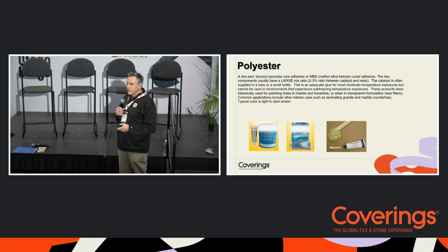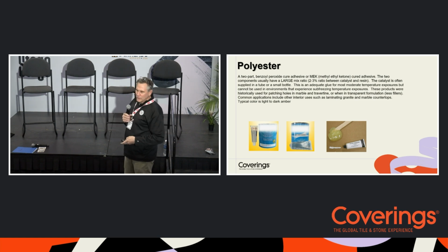And here, polyesters have probably been around for ages, and this is probably the most popular over the years. I don't recommend polyesters for exterior, just because of the shrinkage issue, and they just don't hold up outside. Usually with these, it's a peroxide cure. If you're not used to using them and you don't know a lot of materials, this is a big giveaway. If it's a peroxide cure, it's a little white tube, cream hardener, and it's usually like a 50-to-1 ratio to set it off. Sometimes when you start adding more of the hardener, it heats up and you're going to get some cracking. You'll see it in a mass when you're mixing them.